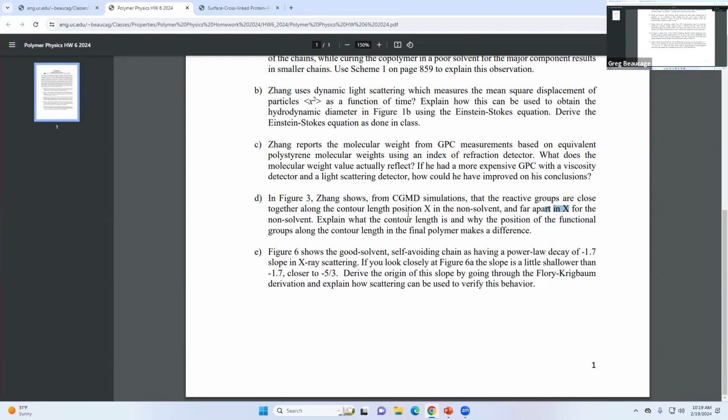So a polystyrene of 100,000 molecular weight, like normal Scotch tape container type polystyrene, the clear stuff that breaks when you squeeze it. The chain on that is going to be 10 nanometers. Like if you measure the end-to-end distance of the chain, it is 10 nanometers. But if you take that chain and stretch it out totally, it would be basically like 300 nanometers, something like that, right? So it's all in this more compact structure because it's a random walk. So it's going to be like square root of n instead of n, right? So it's going to be a big difference.